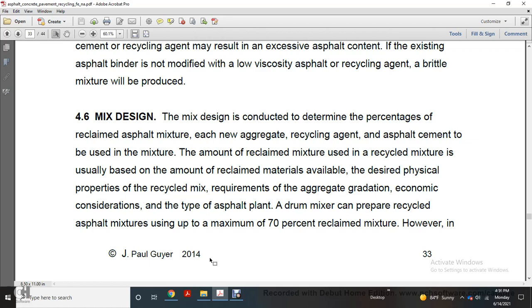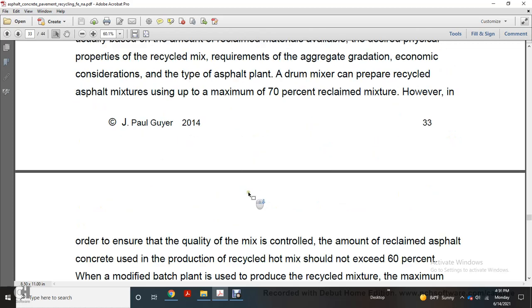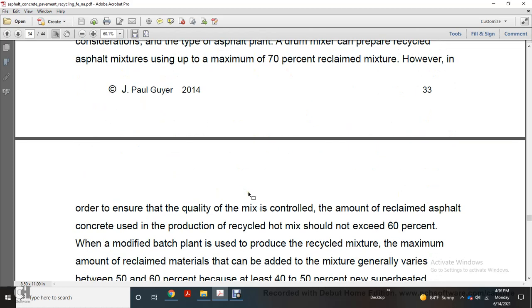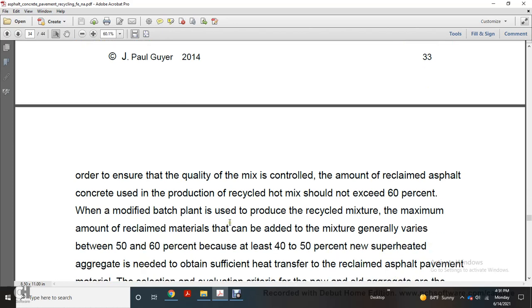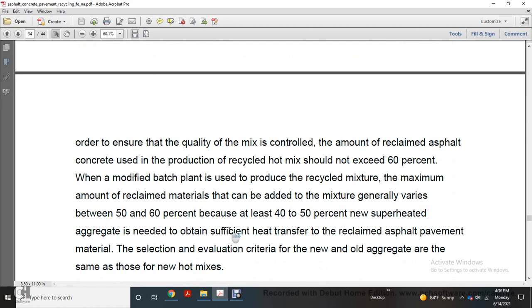The drum mixer can produce a recycled asphalt mixture with a maximum of 70% of the reclaimed mixture. However, in order to ensure the quality of the mixture and control the amount of reclaimed asphalt concrete production, the recycled hot mixture should not exceed 60%. For a modified batch plant with recycled mixture, the maximum amount of recycled material generally varies between 50 and 60%. Because of the remaining 40 to 50%, new superheated aggregate is needed.